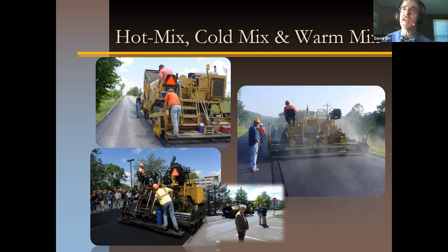And then a third way to do that is warm mix, where you heat it up a little bit more than cold mix. So you've almost got a liquid form, and then you either add a chemical, a wax, or you make it into a foam by blowing air through it, which allows you to coat the rocks. At the end of the day, it's still asphalt. It's still rocks. It still comes from plants. You're just going to have some minor variations in how you place it and how you roll it. But the point is, make sure you've got a mix you understand and you're using properly.